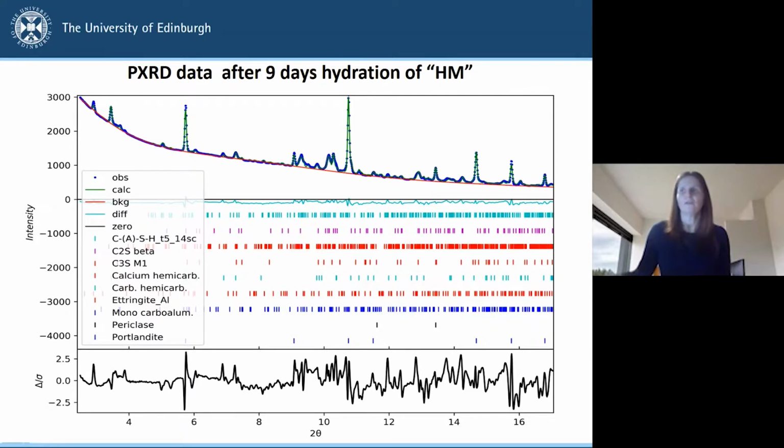So we were able to see after a few days of hydration, we still had some of the alite and belite silicate phases present, but we're finding the presence of some phases that we'd expect to find on hydration of clinker samples. So I should say this is just pure clinker powders that we've obtained from our industrial sponsors with water. We didn't add any gypsum, calcium sulfate, at this point. So we can see portlandite forming and these calcium aluminium silicate hydrate phases forming.